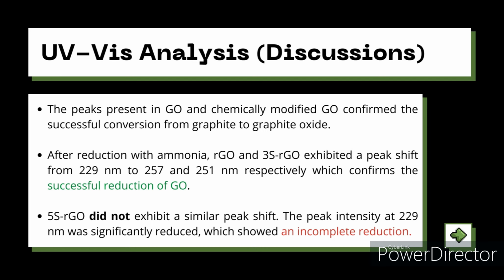This peak shift is due to the restoration of conjugated pi-to-pi bonds between carbon. But for 5S-RGO, the peak at 229 nanometer did not shift. It was only significantly reduced, which confirmed the reduction of 5S-RGO, but it is incomplete.